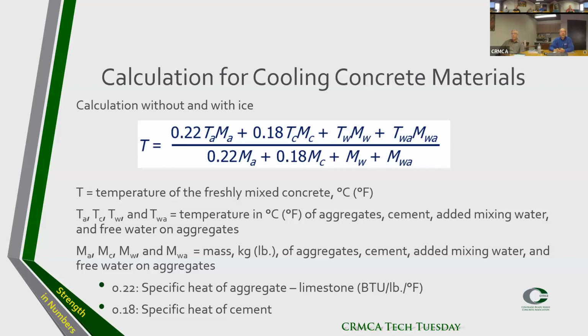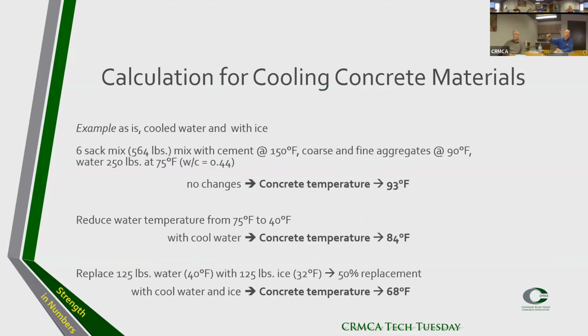Calculation for cooling concrete materials. This is the calculation that's here out of the booklet. I'm not going to go into it. This is really up to the ready mix producer to do some of the calculations. I just have an example here, cooled with water and cooled with ice. If you have a mix where cement is at 150, coarse and fine aggregate at 90 degrees, so we're in July, and water, 250 pounds at 75, if we just mix that together based on the calculation that we saw before, the concrete temperature is going to end up around 93 F.